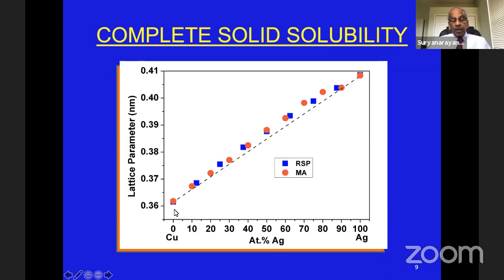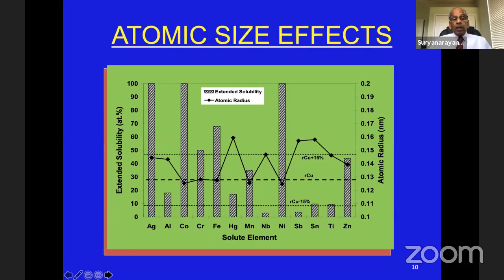You can see they form continuous series of solid solutions, whether it's by RSP or by MA, there does not appear to be a significant difference between them. Both of them do have a slight positive deviation from the Vegard's law prediction of variation of lattice parameter with the solute content.